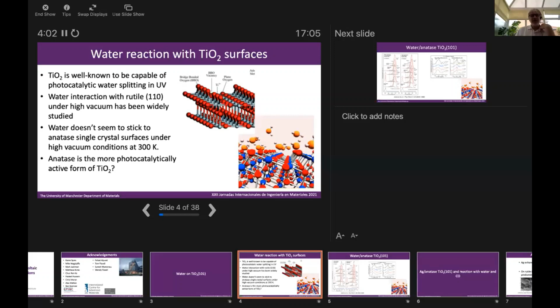And the only way they could get any reaction was to cool the surface down, cool the crystal down to kind of 100 Kelvin or so, condense water ice onto the surface, and then allow the sample to warm back up to room temperature. And under those conditions, they then found that there was actually some surface hydroxide formed on this anatase surface. So this is the anatase 101 surface that I'm going to be talking about. So this is the rutile 110. So we were interested in this.